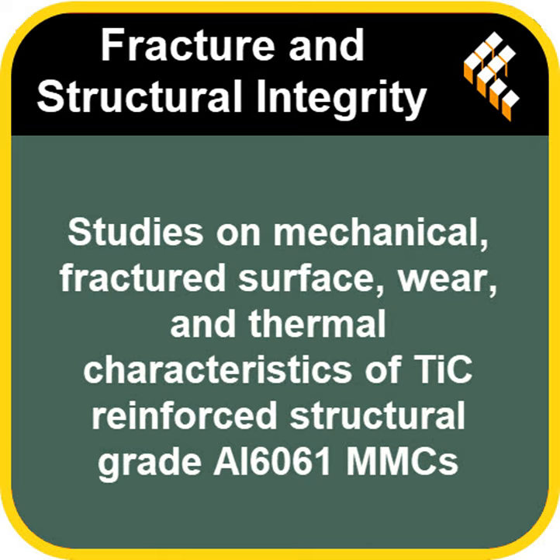The study observed a remarkable 51% increase in overall hardness for the composites. 51%, that's huge. It really is. Shows how effective these particles are at hardening the alloy. Okay, here's where it gets really interesting for me. They tested various percentages of TiC, right? 3, 6, 9, 12%. Was there an optimal amount for these mechanical properties, or was it just a case of more TiC is always better?